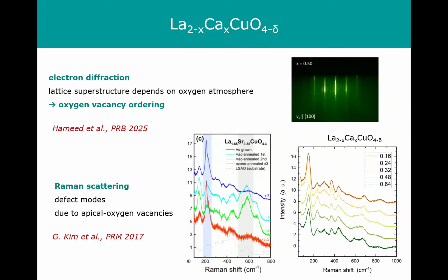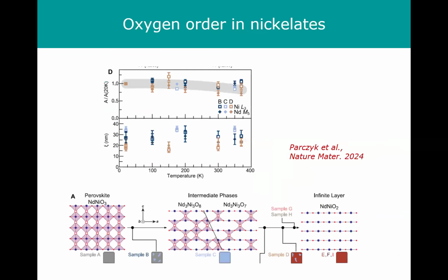And on the right-hand side, these are unpublished data on lanthanum calcium copper oxide, where you see a lot of regular phonons, but none of these pronounced defect peaks. So that means that indeed, in the lanthanum calcium system, the prevalence of defects is much reduced compared to lanthanum strontium copper oxide. And in some sense, these findings are similar to phenomena that have recently been reported in nickelates.